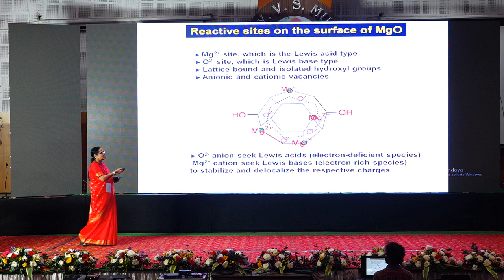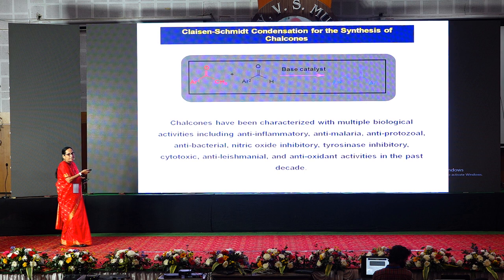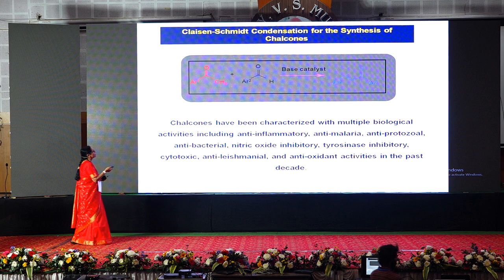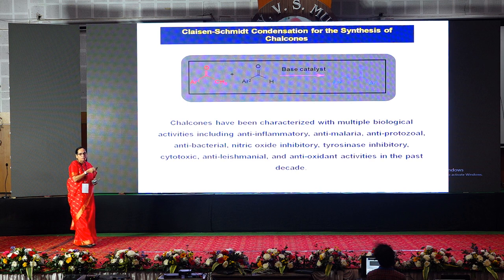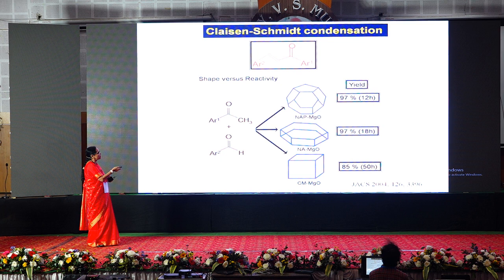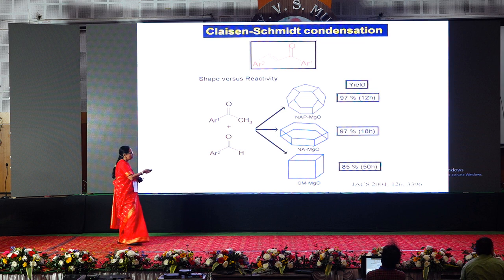So what we have done is, you can see this reaction is a base catalyzed reaction, and we took this nano magnesium oxide and we did the Claisen-Schmidt condensation, and you will get the chalcones very easily, because all the chalcones are very important products in pharmaceuticals. And you can see when you use the nano magnesium oxide, the reaction gives 97% yield in 12 hours, whereas the commercial magnesium oxide gives 85% in 50 hours.